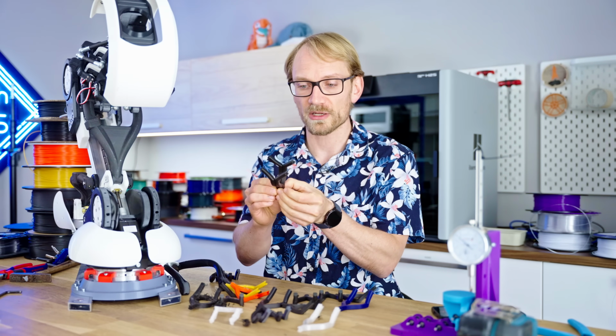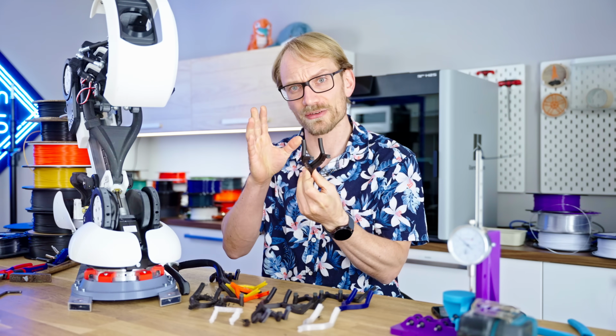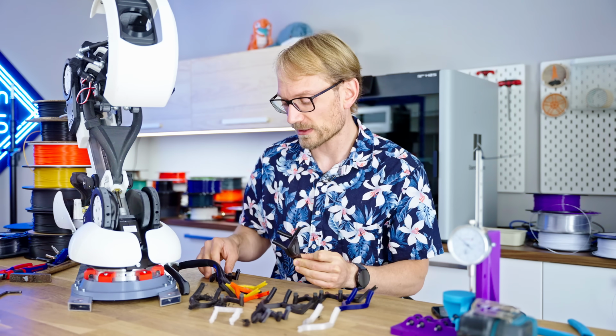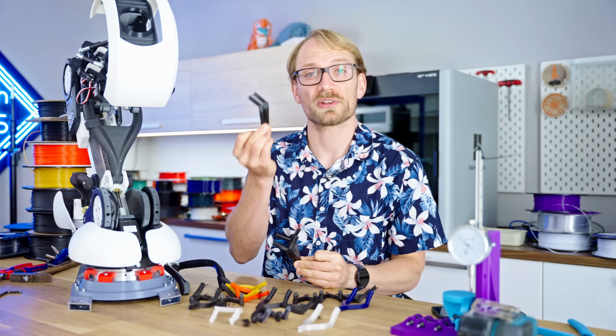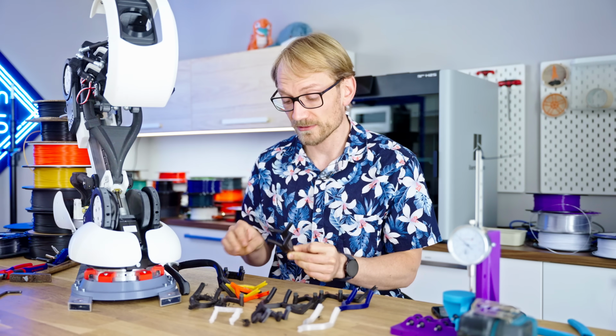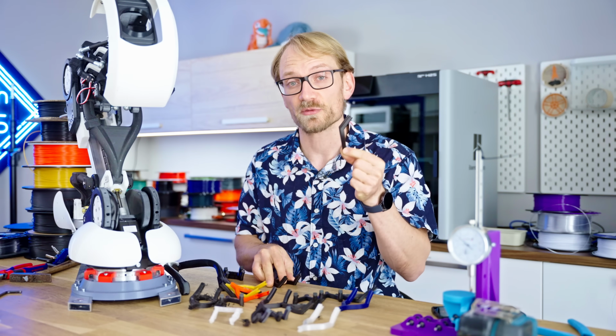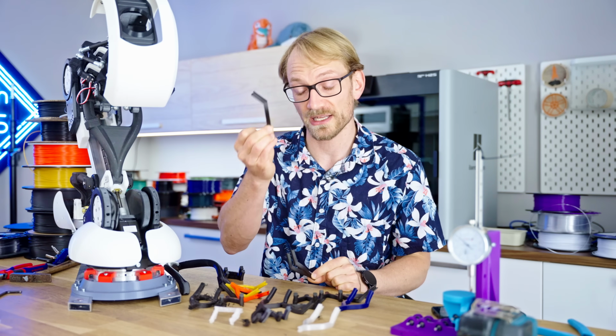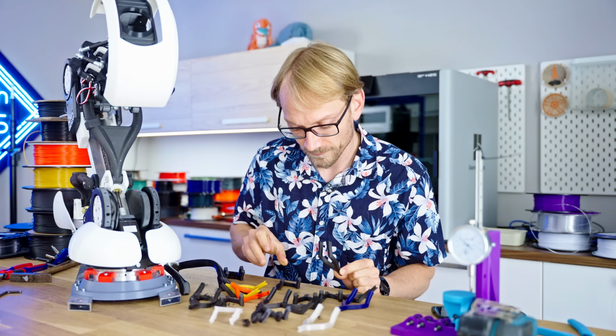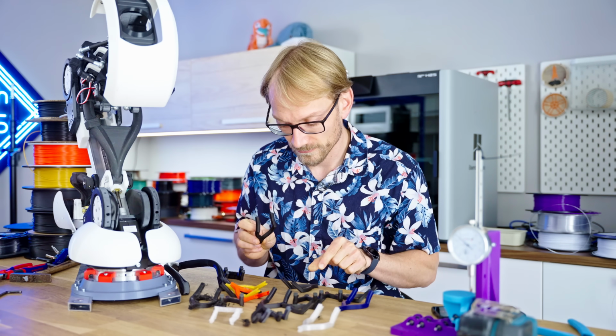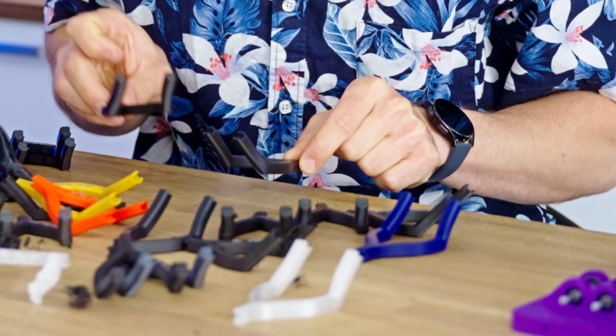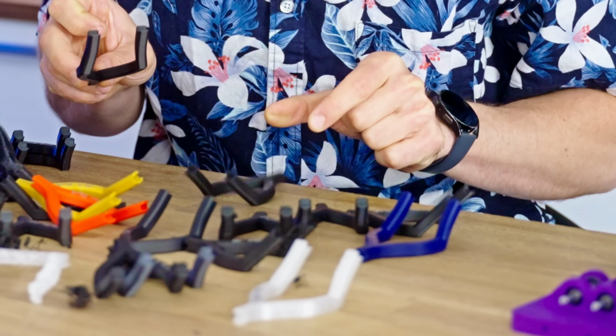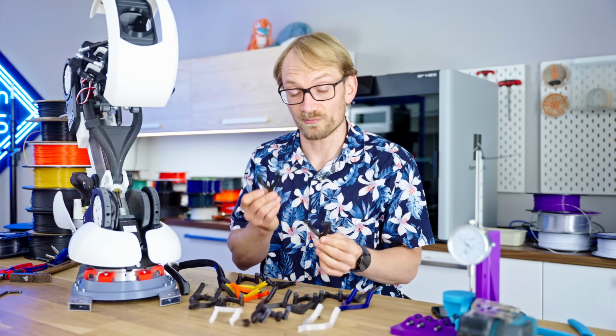So these only shrunk by, I measured these, about 0.5% for the carbon fiber one and roughly 1% for the non-reinforced one. And you can tell how much more rigid it is just by the sound that they make. So let's drop the standard HDPLA carbon fiber and the treated one. So the heat treating in this case, I think, did a really good job.